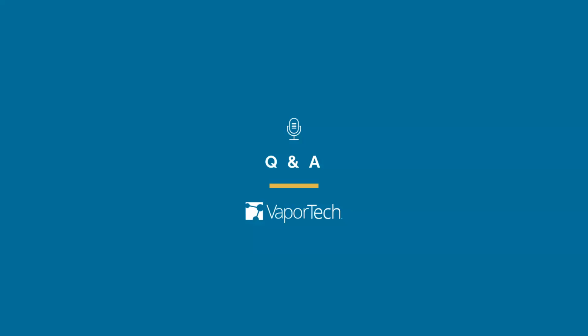While in the PECVD process, you start just by putting gases or vapors inside the chamber. What I mean by vapors is a source that is a liquid at room temperature and pressure. As you introduce that into a vacuum chamber, it becomes a vapor, and part of that vapor becomes part of the coating. So that's more or less how it works.